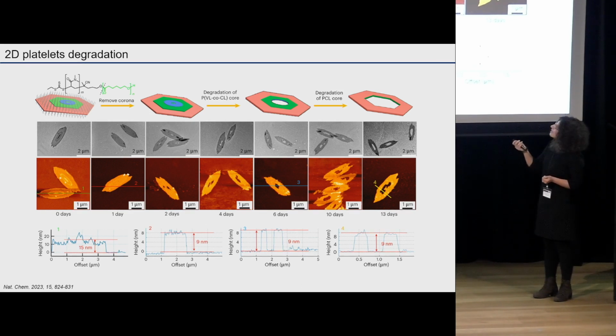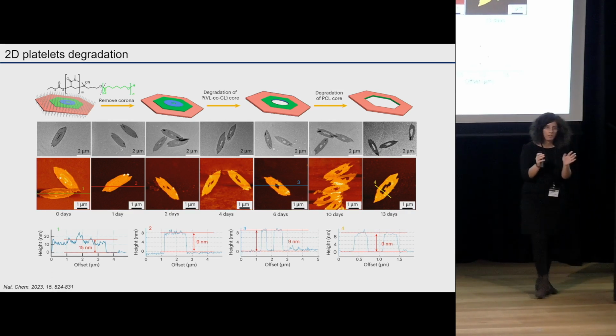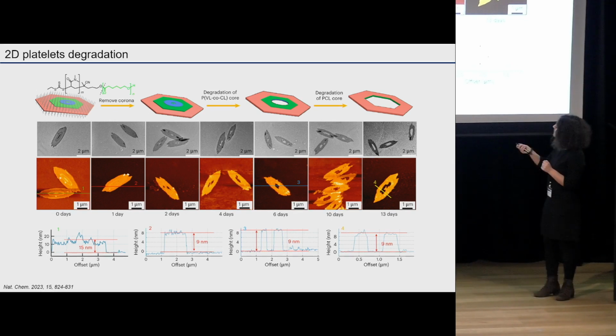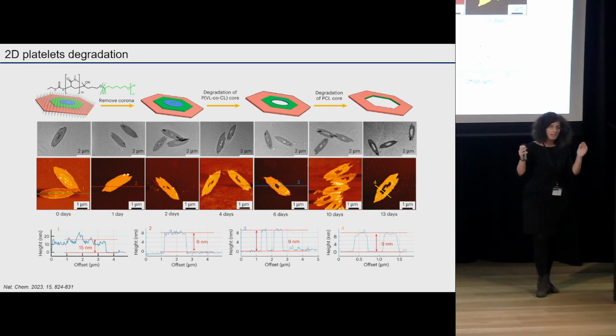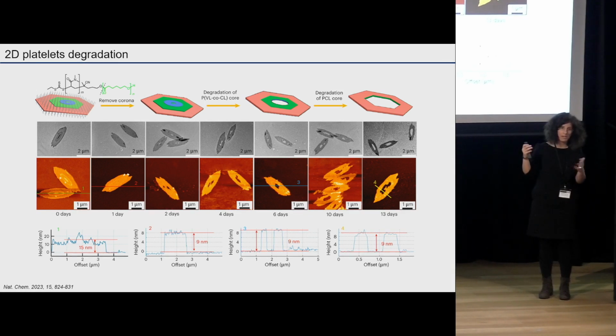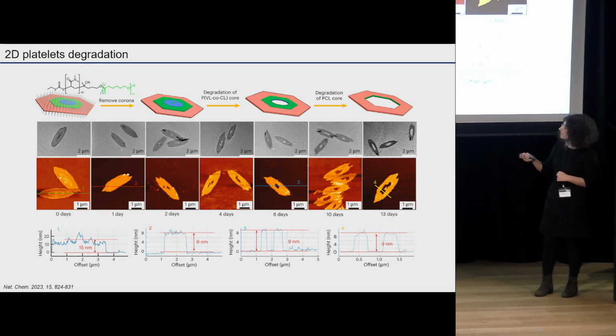starting point. And as you can see, we first degrade the blue bit in here, which is the 6-member ring monomer that we were using. And that happens between the first 2 days. And then as we go further, in about 13 days, we degrade also the 8-member ring monomer that we had in our polymer. And so we can control the degradation by controlling the nanoparticle composition. And you can study that very well by using AFM and looking at the height of the nanoparticle and how it goes from 15 nanometers to 9 nanometers.